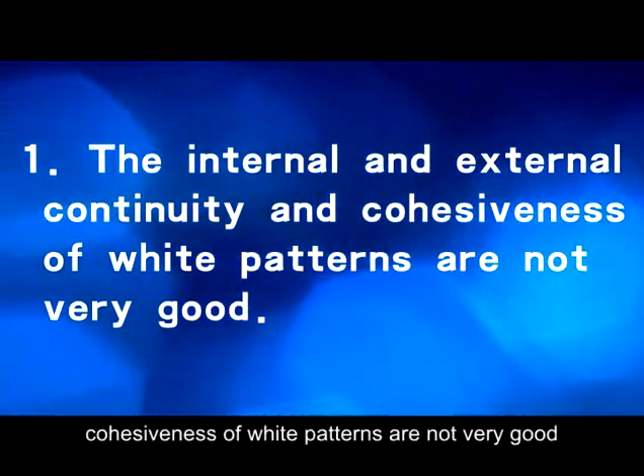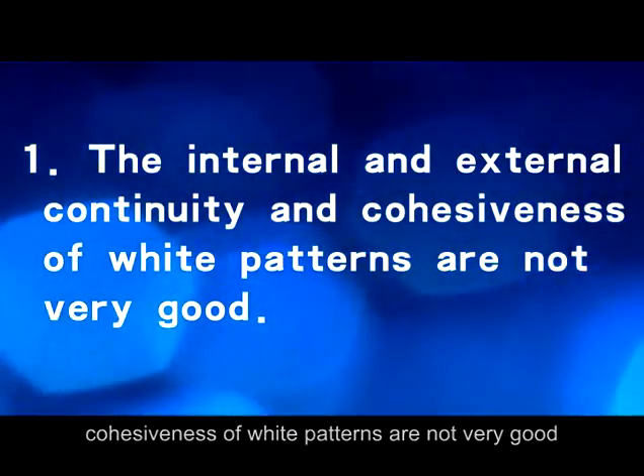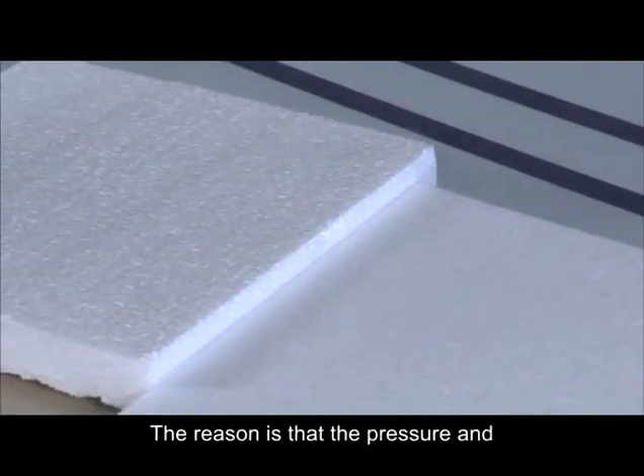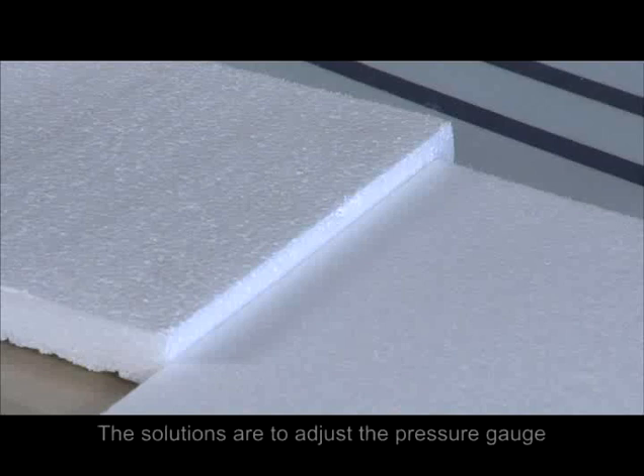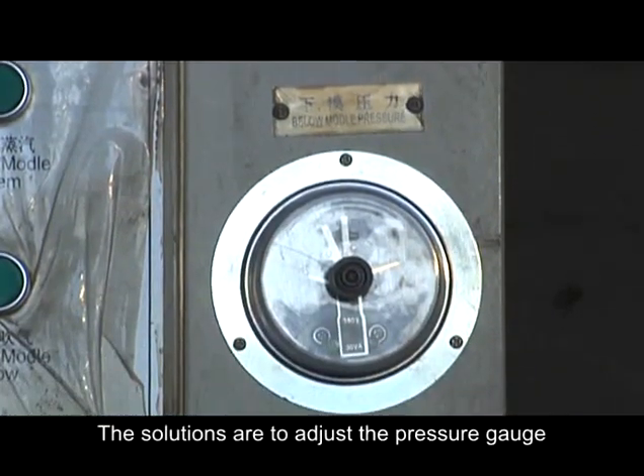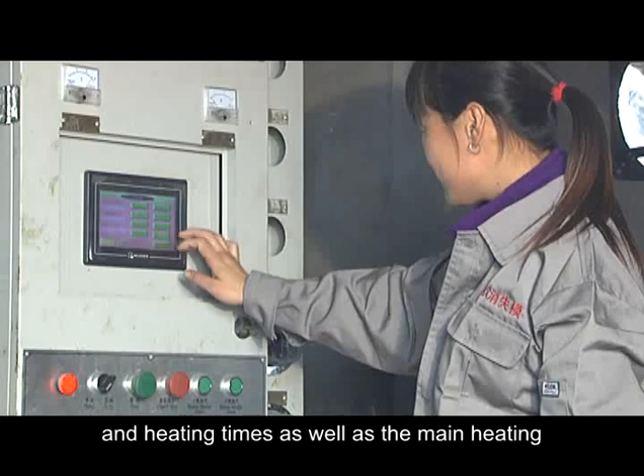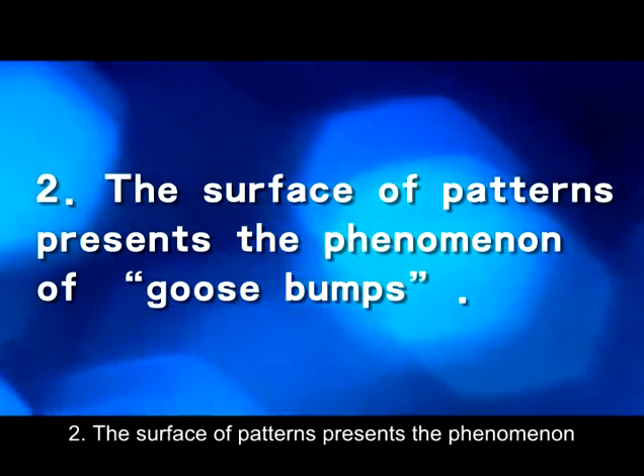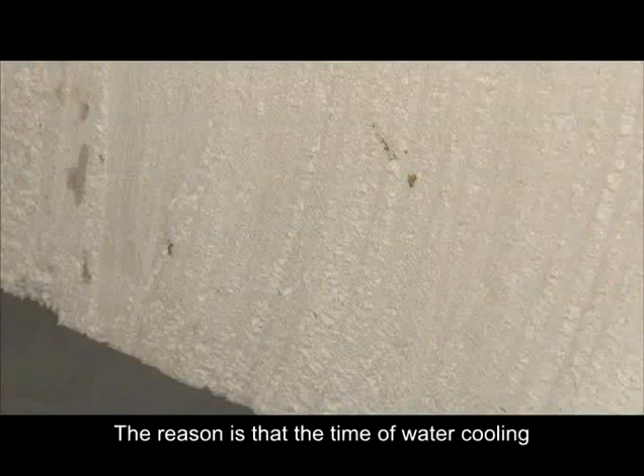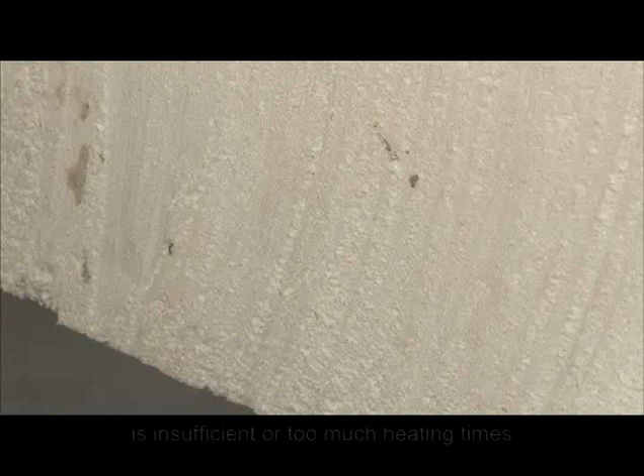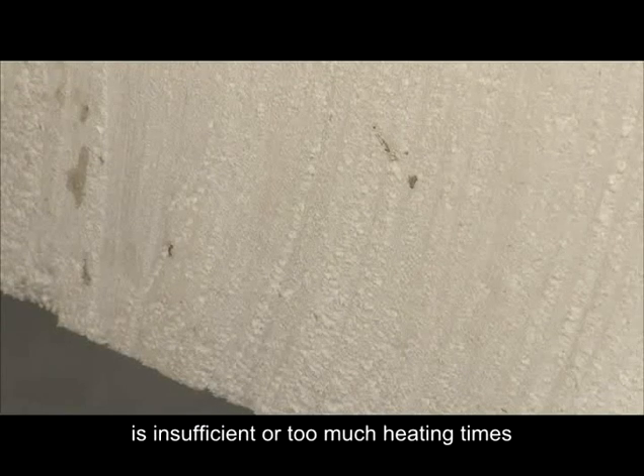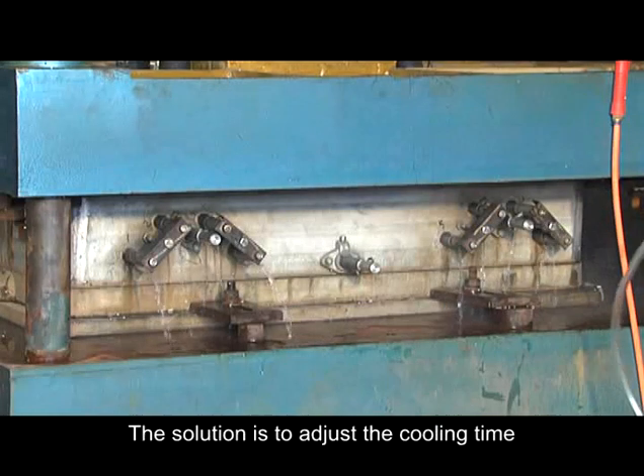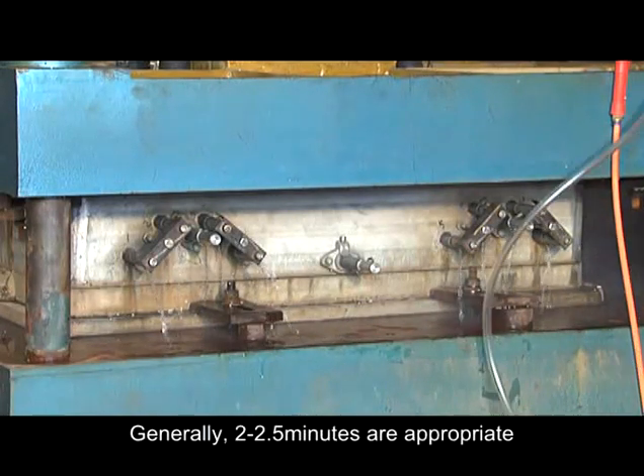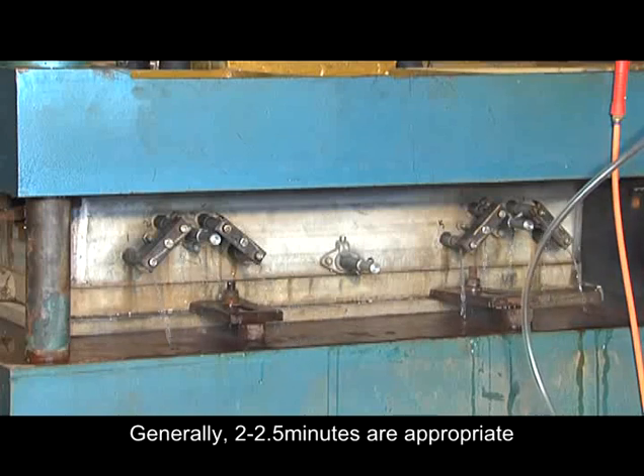1. The internal and external continuity and cohesiveness of white patterns are not very good. The reason is that the pressure and times of heating are not enough. The solutions are to adjust the pressure gauge and heating times as well as the main heating. 2. The surface of patterns presents the phenomenon of goose bumps. The reason is that the time of water cooling is insufficient or too much heating times. The solution is to adjust the cooling time. Generally, 2 to 2.5 minutes are appropriate.